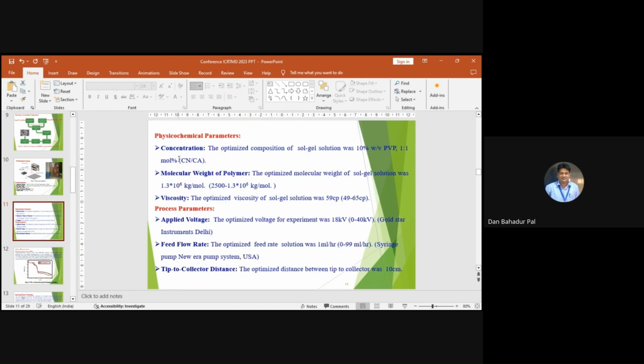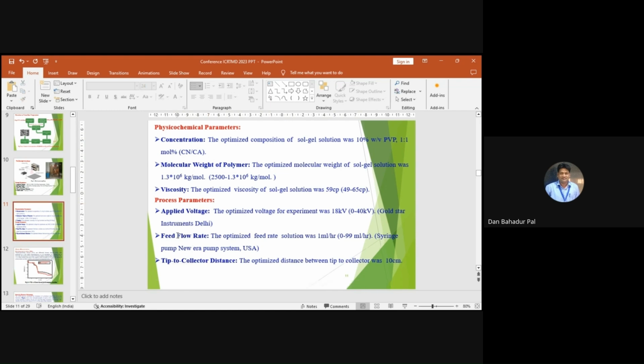So these are the physicochemical parameters. First is the concentration. We have optimized the composition of the sol gel solution: 10% weight by volume PVP and 1 to 1 mole % cerium nitrate and copper acetate. Then the molecular weight of the PVP is 1.3 into 10 power 6 kg per mole. Viscosity, we optimized the solution around 59 centipoise. For the process parameters, we have taken the applied voltage of 18 kV, the feed rate around 1 ml per hour, and the collector to tip distance of 10 centimeter.